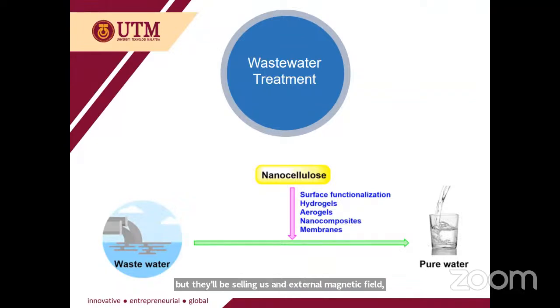So through directly altering the nanocellulose surface via sulfonation, amination, and carboxylation, and adjusting key variables like pH, adsorption load, temperature, and agitation speed, it is possible to enhance the retention of these dangerous metals by adsorption from aqueous solution. Currently, a large number of businesses all around the world produce enormous amounts of nanocellulose from readily available lignocellulose materials at low cost, but advanced research in adsorption must be carried out using real wastewater and more potent adsorbents for scaling up the laboratory assays.